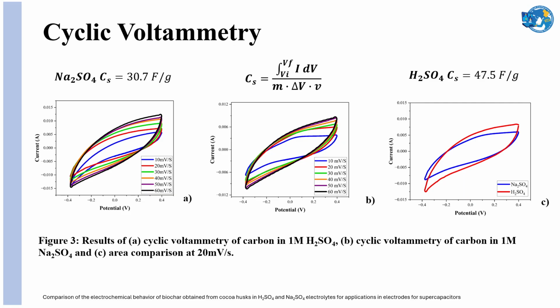This material predominantly exhibits electrical double-layer capacitor mechanisms, which are characteristic behavior based on ion exchange at the electrode-electrolyte interface. Furthermore, the material behaves as a resistive capacitor, which produces a wider angle in the shape of the quasi-rectangle. Comparing the results for the two different electrolytes, it is noticeable that the sulfuric acid electrolyte allows for a larger quasi-rectangular area due to its higher ionic conductivity, smaller ion size, and proton-driven conduction mechanisms, resulting in a higher specific capacitance.